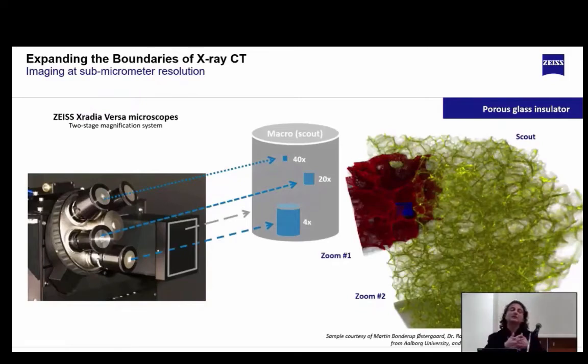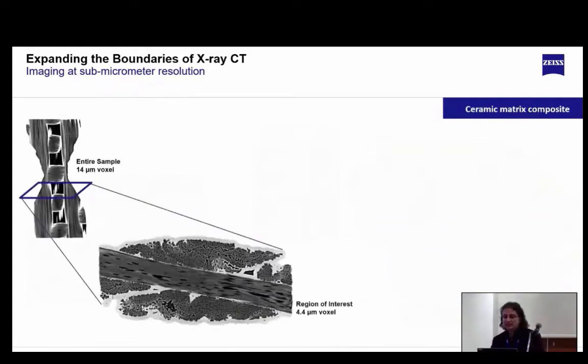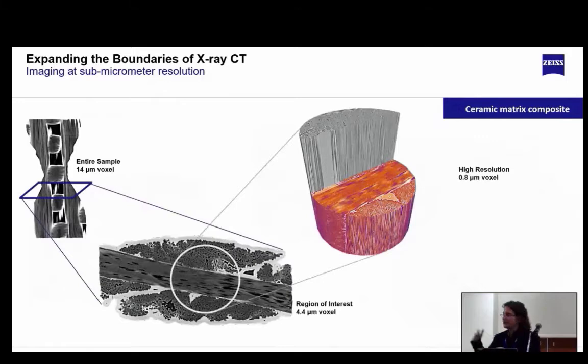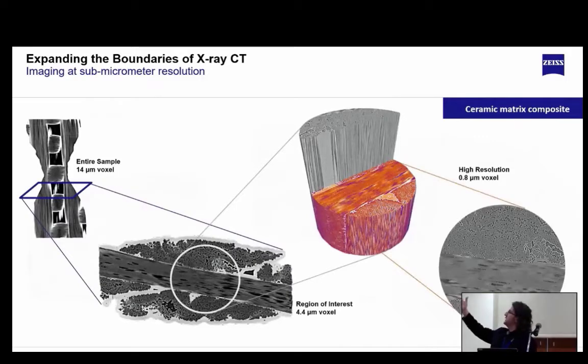This technique can be applied to several types of samples. For example, ceramic matrix composite, applying the same principle. The idea is basically the same. You zoom in and you can see how we get the entire sample at 14 micrometer voxel size. And using the optical magnification, you can get regions of interest at 4.4 and even 0.8 micrometers voxel size. And you can see the level of detail that you can obtain in this composite sample.